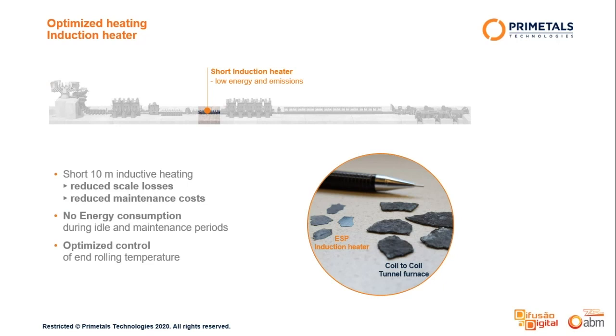Optimized heating is possible with the 10-meter short induction furnace. Short heating at high strip speed means reduced scale loss, and this means increased yield compared to tunnel furnaces. Additionally, such a short furnace requires drastically reduced maintenance efforts. During any operational break, the power can be completely switched off. Finally, important is the fact that the induction heater is built up of 10 modules, which allow optimized control of the temperature with immediate feedback.